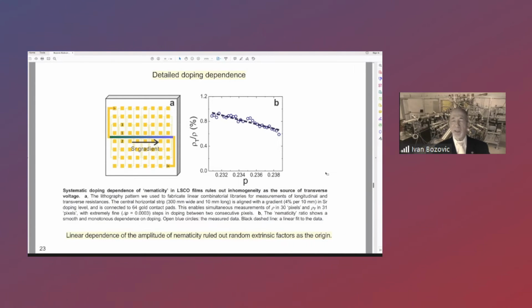Here is the same thing except magnified by a factor of 100. What I mean by that is that here we have used a technique that we call combinatorial molecular beam epitaxy, meaning that we have deliberately created a small gradient of strontium along this central bar. The variation is about 4% over 1 centimeter, which then translates to the doping changing in extremely fine increments, 1% of 1% from one pixel to another.